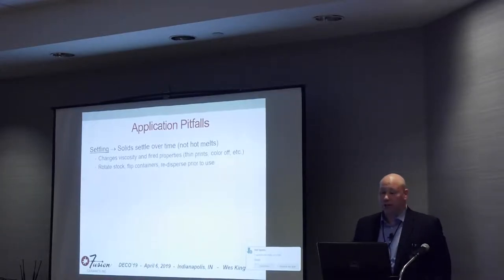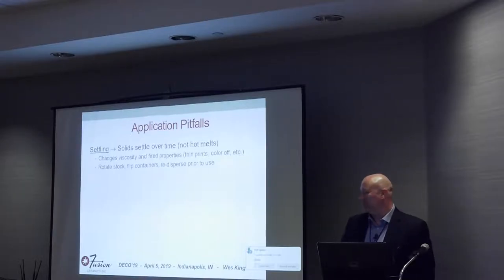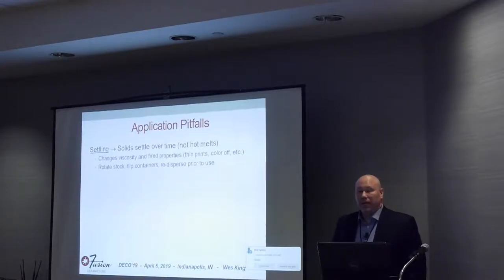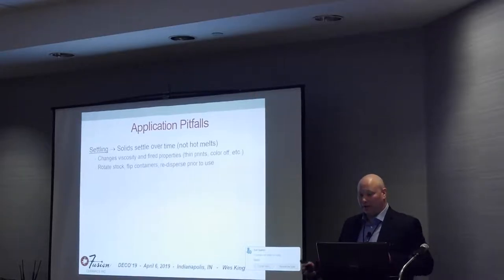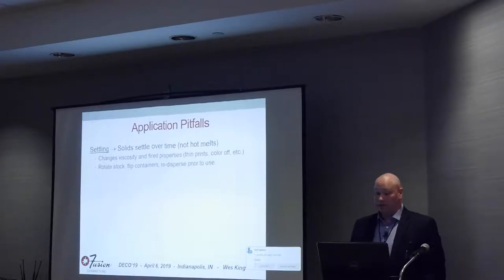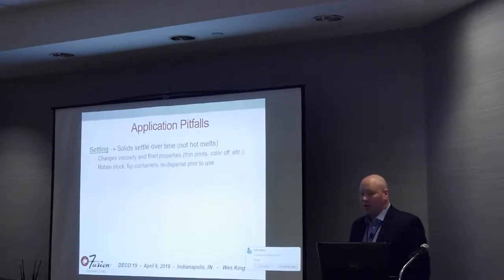Starting with the pitfalls: in a wet product, the solids settle over time because of density differences. If you're not careful to re-stir it properly and get everything mixed uniformly, you can have a different viscosity than expected—you'll have thin material on top and thick material on bottom. Fired properties could include thin prints and different color. We recommend rotating stock, flipping containers, and redispersing prior to use if you're going to hold on to the material a long time. If kept tightly in the container, a wet paste can last for many years.